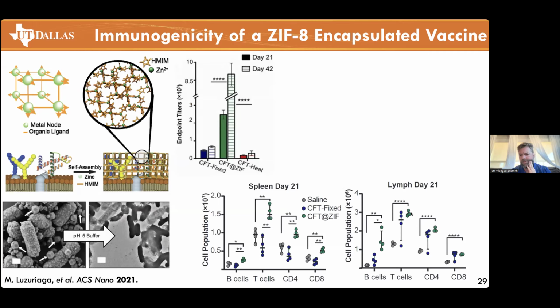I'm going to direct you to the lymph data over here on the right. The blue is the fixed formulation, and the green is the MOF formulation. In the local lymph node, T cells are roughly the same, much higher, obviously, than baseline. What's different, though, is the total B cell production, and that's significantly higher in the lymph node. But it's even more telling that in the spleen, which is indicative of a more systemic immune response, they're all higher. So we have much higher B cell, T cell, and CD4 and CD8 production. And so the immune system with the ZIF formulation is clearly way more immunologically active.